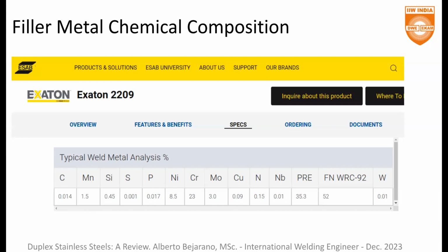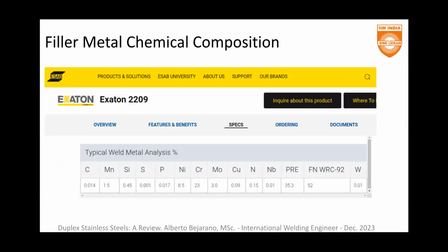So this chromium, in a little zone, is normally localized in the grain boundary, which is a very, very big problem for us. Okay? So in this case, we could have the same problem. So we don't need high carbon in our alloy. This is the reason the filler metal has even less carbon than the base material.